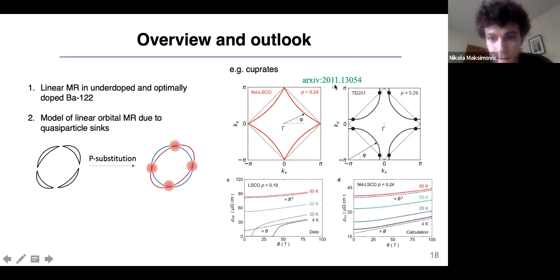This is from Brad Ramshaw and Louis Taillefer's recent paper on cuprate magnetoresistance. And they were able to observe just simply using a Shockley tube integral that the magnetoresistance in high fields can be linear if you have very anisotropic scattering.